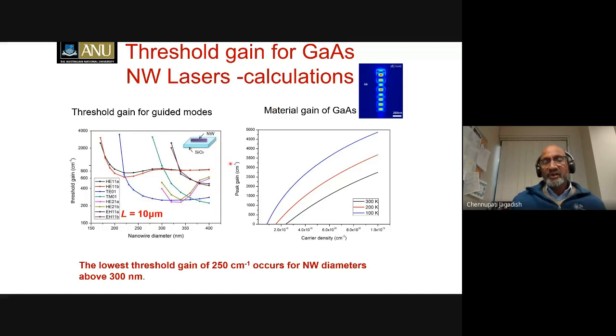Again, Drew has plotted the peak gain as a function of the injected carrier density. And again, this threshold-like behavior, which I was showing you earlier, and which is again threshold. The carrier density needed is very much dependent on the temperature of the device as well. That's what you would expect. And again, in that lecture, we talked about that one, for example.